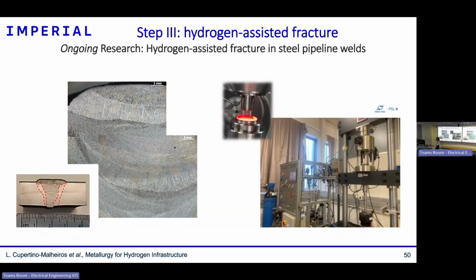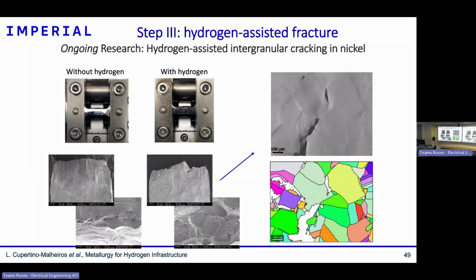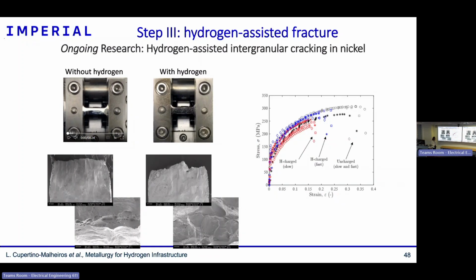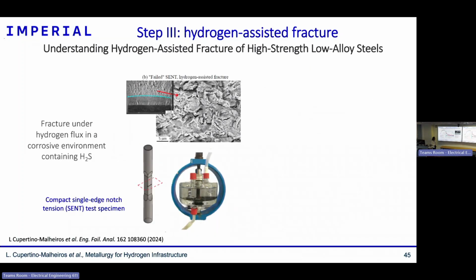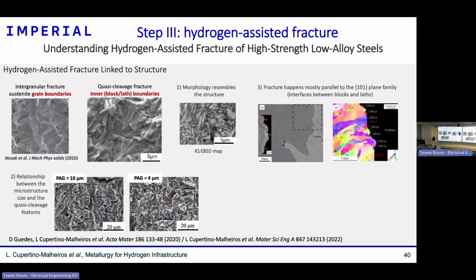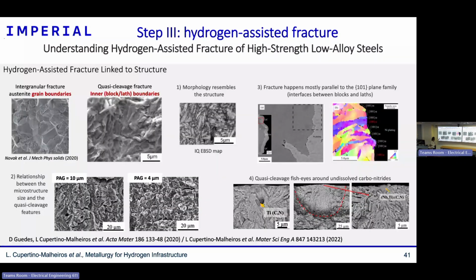Quite a few online questions. Someone's asked, regarding hydrogen embrittlement mechanisms and the permeation tensile machine, have you identified any dominant mechanism? I mean, this is a question that is very debatable in the literature. What we see with those tests, when you look at the fracture surfaces in the structure, it points out that interfaces are breaking. So it seems that there is some sort of decohesion mechanism that is causing the fracture.